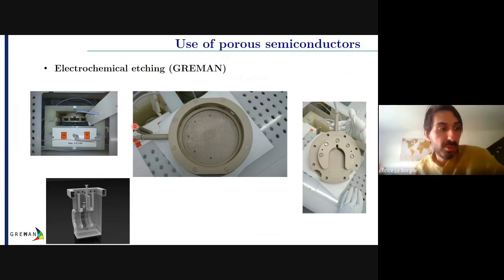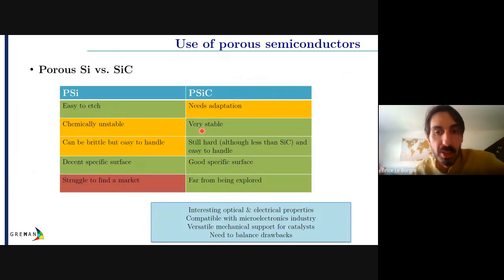To conclude on that, on the fact that it can be really industrially viable, we use a 6 inch etching cell at the GREMAN laboratory. So it's really compatible with the industry. And of course, reproducibility and homogeneity is something important for industry. So we also have not to focus on small samples, but it's possible to make them larger and to convince the industry that we can use this material for the market.